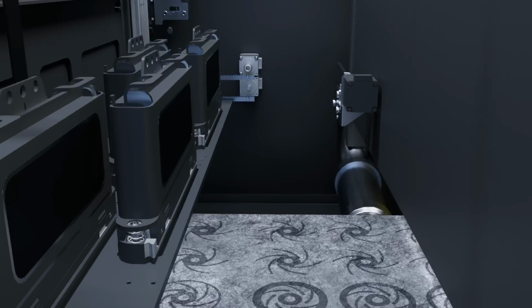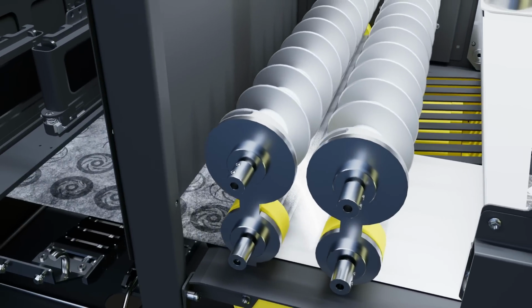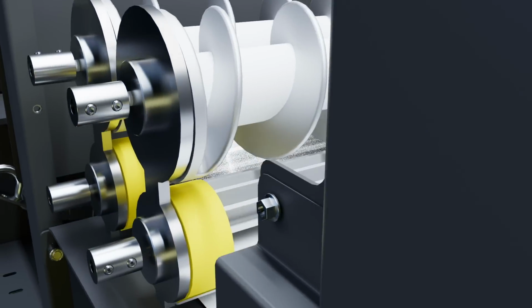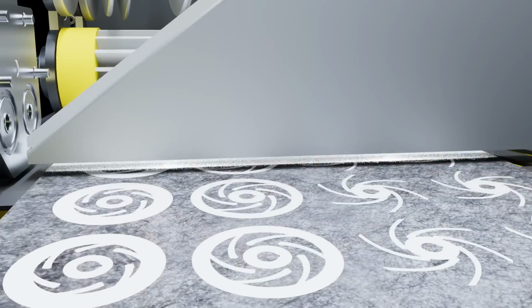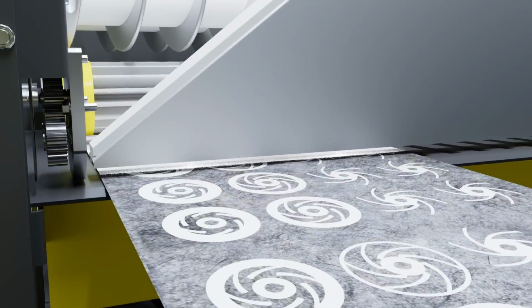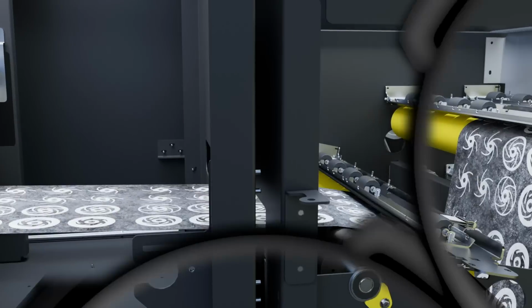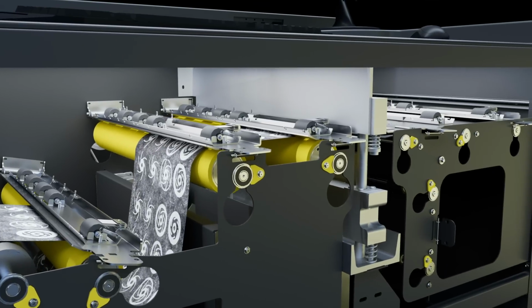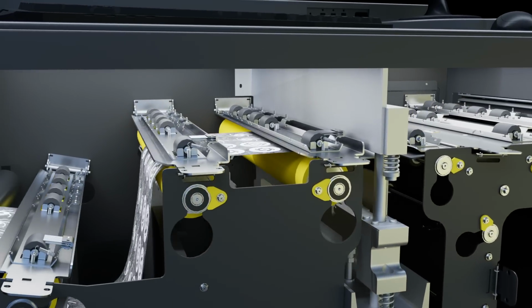The web passes through a powdering system where polymer powder is flooded onto the web. The powder sticks to the web where the fluid is deposited. The excess powder is vacuumed off and the polymer is selectively deposited on the web. Microscopically, you can see polymer particles penetrating the fiber web. The machine prints continuously, cutting the web into individual sheets.